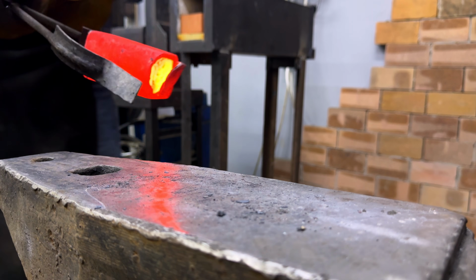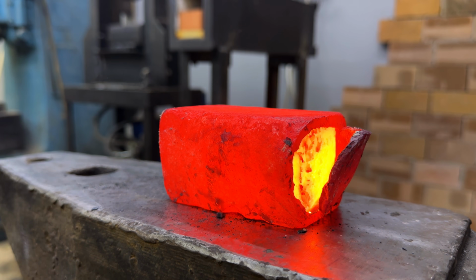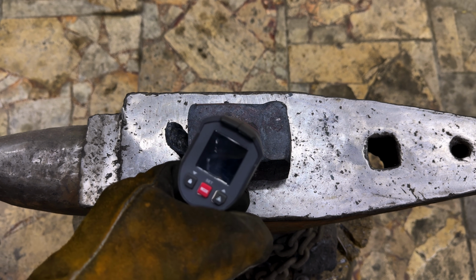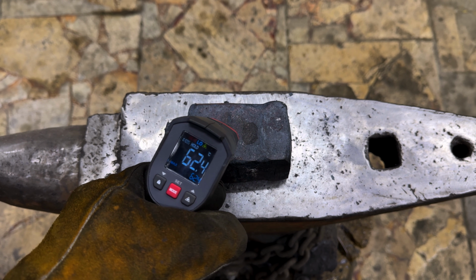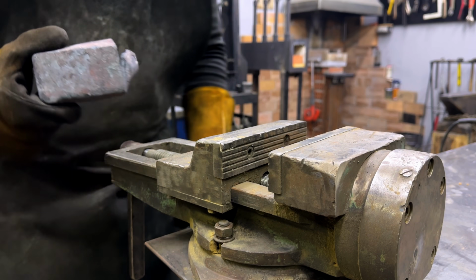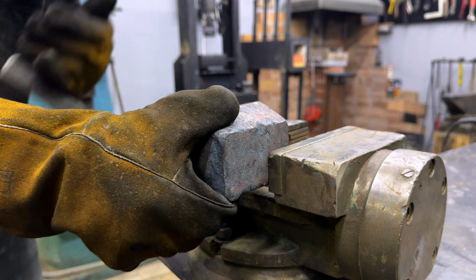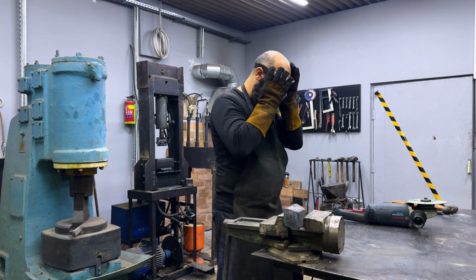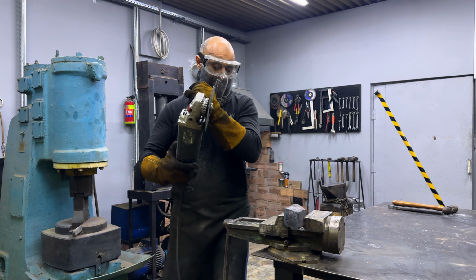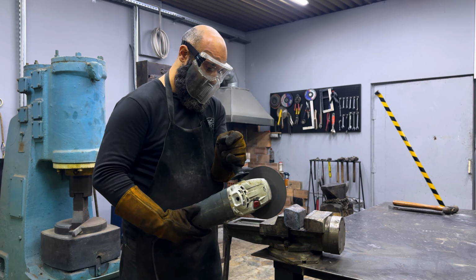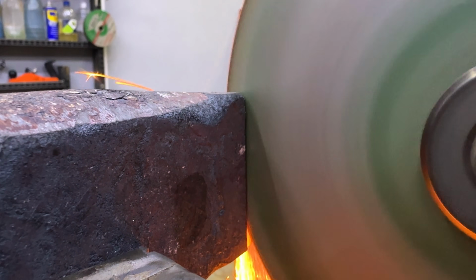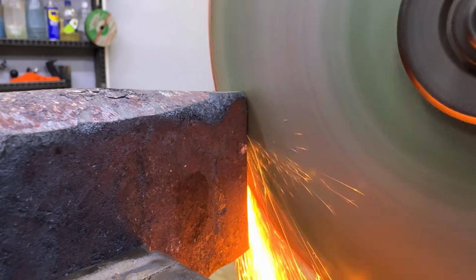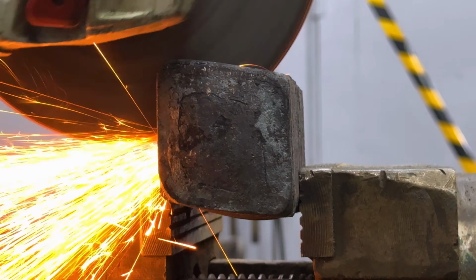First weld is done. Let it cool a bit, then check the temp. You want to know where you're at before the next heat. Now we cut the billet open to inspect the weld and multiply the layers. Angle grinder sparks are hot and they will find your eyes if you're not careful. Cut through the billet. You're looking for clean, solid welds inside. Dark lines or voids mean the weld failed. Grind them out or they'll haunt you later.